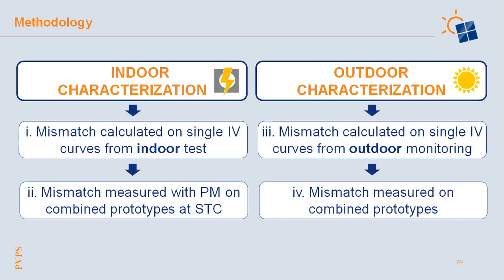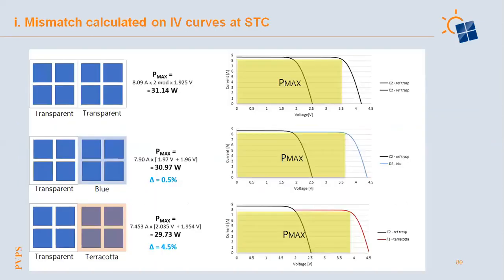Similarly, for outdoor characterization, we calculated the mismatch on single IV curves from outdoor monitoring, and then we measured the mismatch on physically combined prototypes. Here is an example of how we calculated the maximum power for the prototypes combined in series by evaluating the IV curves. So we merged the IV curves obtained from the power measurement test, and we considered the maximum power point to calculate the maximum power, the yellow area.